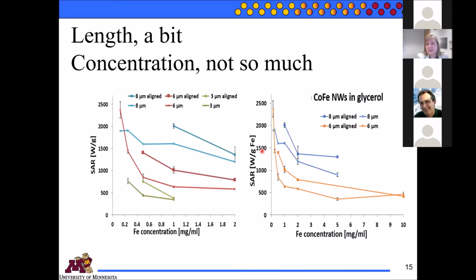It turns out that length matters a bit. These are different lengths. This is 3 microns, 6 microns, 8 microns. And concentration doesn't really matter. So we've gone up to 2 milligram per milliliter here, and we've gone out to 10 milligram per milliliter in this sample because our collaborator was thinking we might need that concentration. We've actually shown that 8 microns aligned at 5 milligram per milliliter is actually a really good heater.